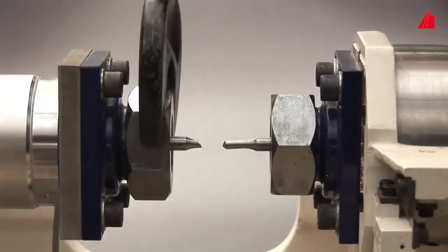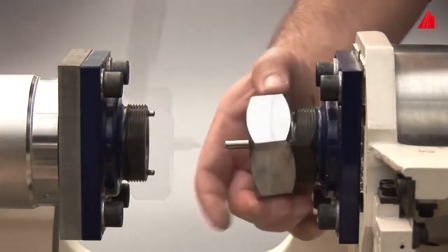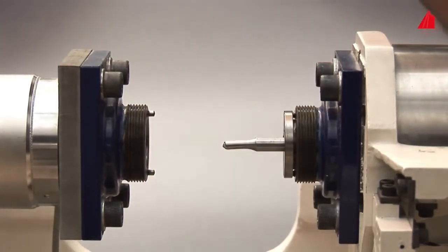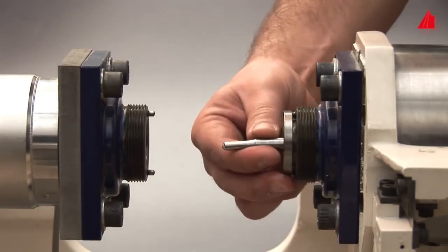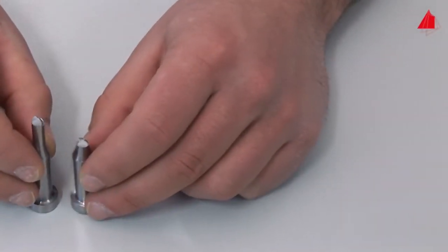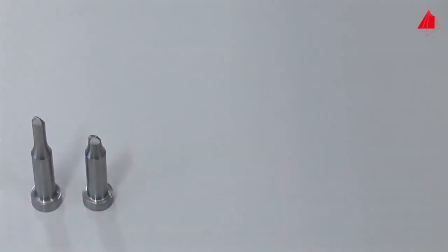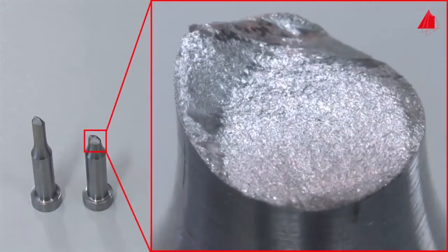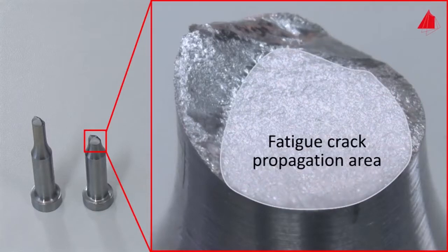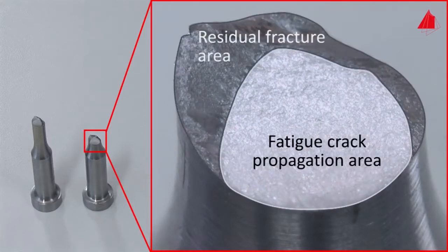The material tester removes the fragments cautiously and inspects the fracture surfaces. At first glance, the fracture surface looks unimpressive. A closer look reveals two regions: the rather dull, predominantly flat fatigue crack propagation area and the rough residual fracture area. The residual fracture area results from the final catastrophic rupture. The fatigue crack propagation area has developed during the cyclic growth of the fatigue cracks starting at the surface of the specimen.